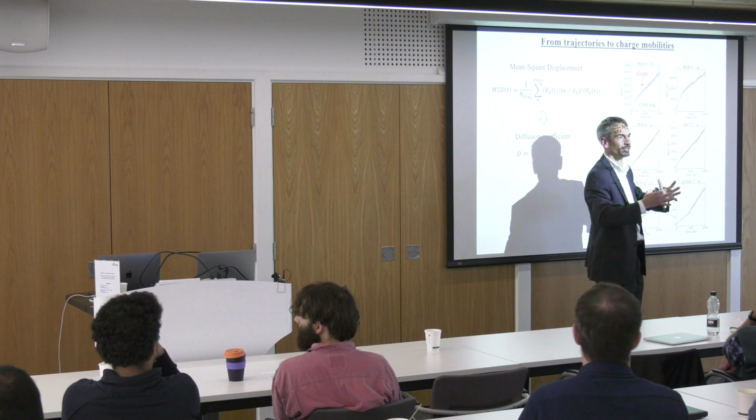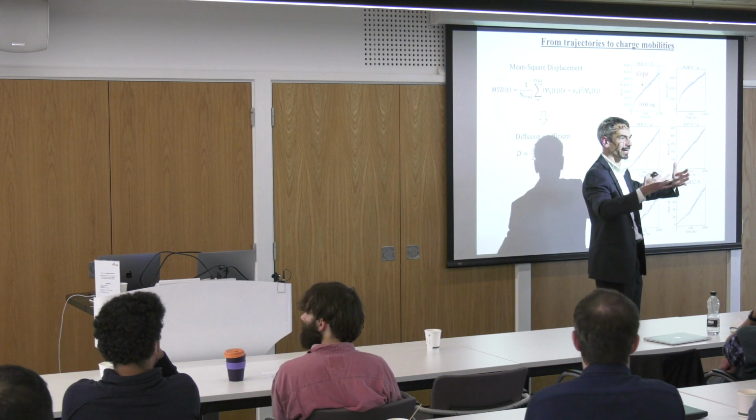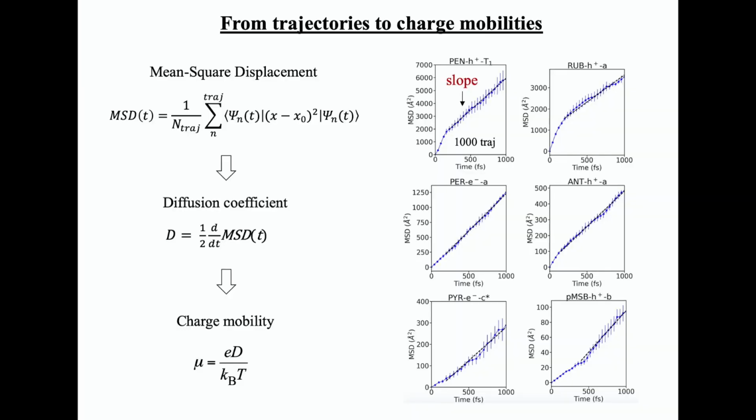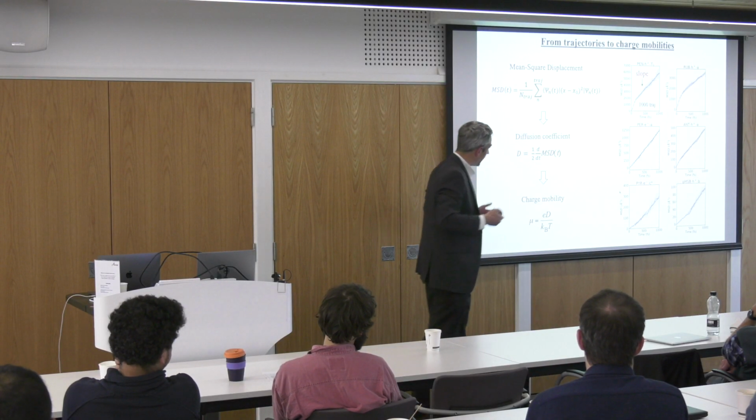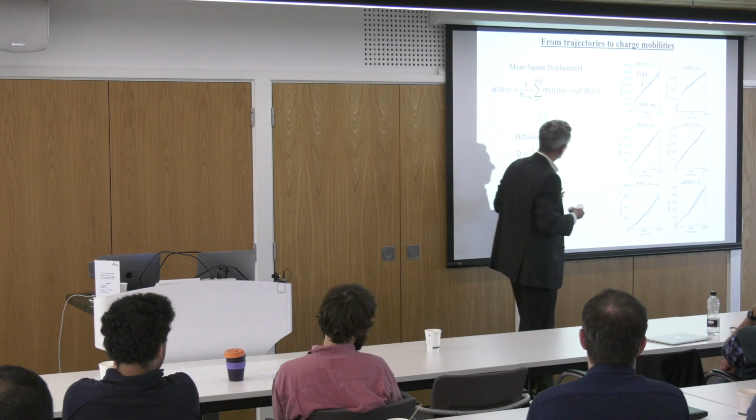This is not Einstein diffusion. This is real quantum mechanics. But then after that process has finished, the real diffusion process is happening. And this diffusion process is always, in all of the substances that we're looking at, linear, so it's indicative of Einstein diffusion. So this delocalized polaron moves in that material with an MSD that goes linearly in time.